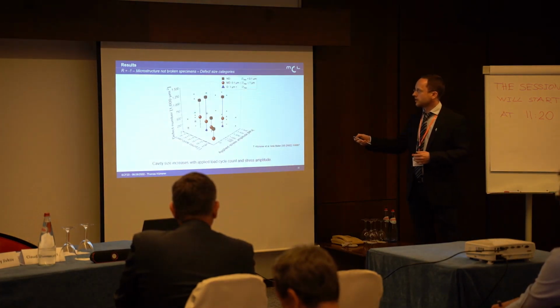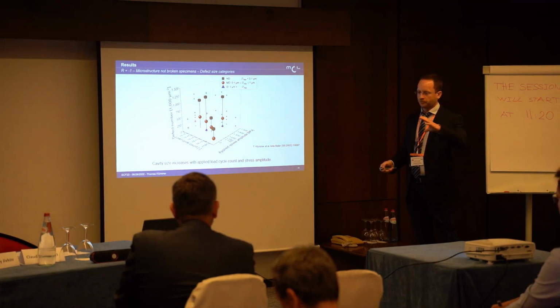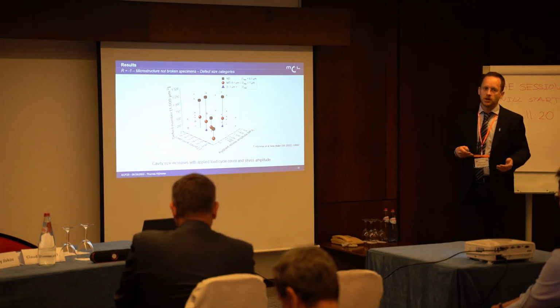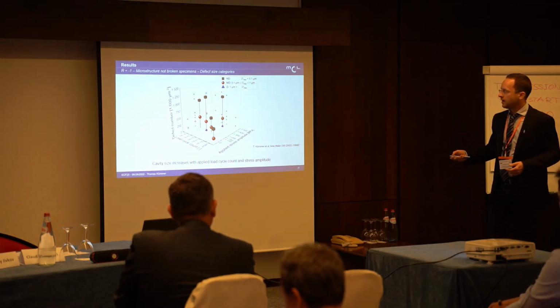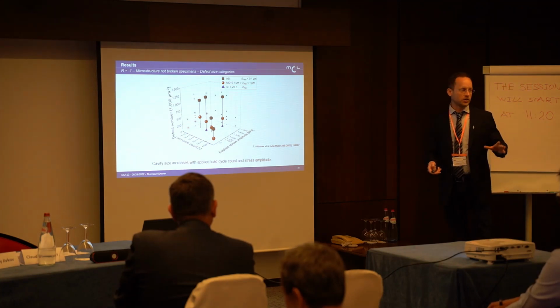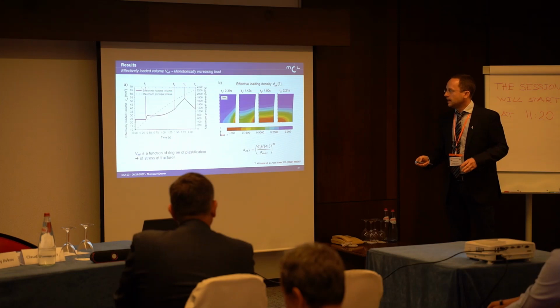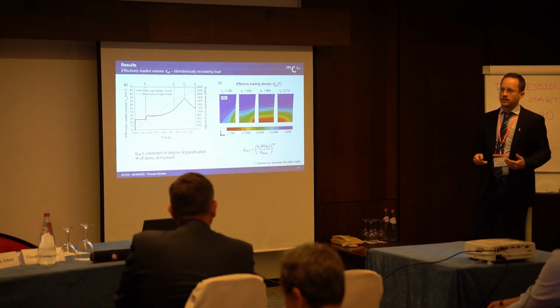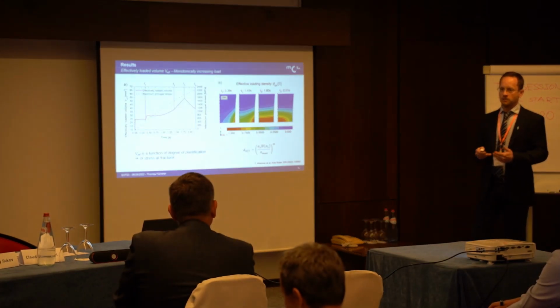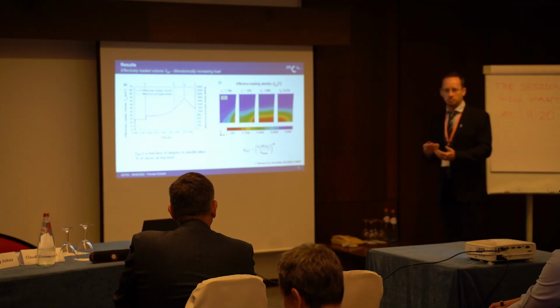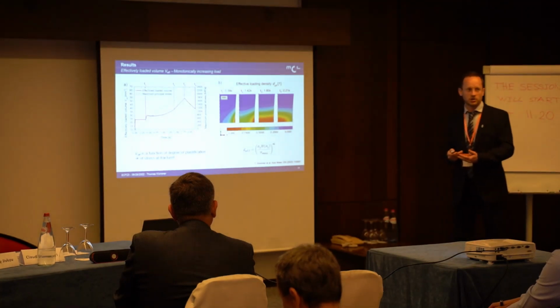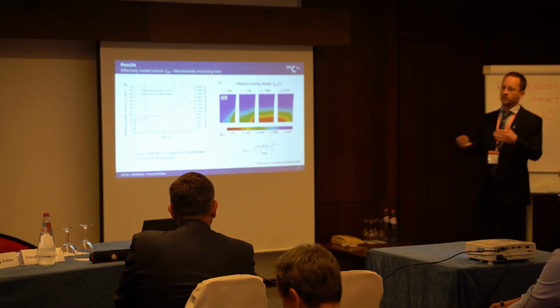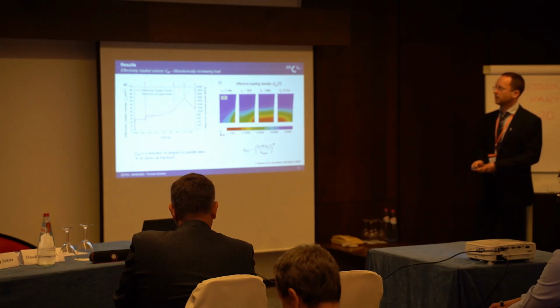But more interestingly, maybe here for the given sizes we looked at of the area, you see a rise with micro defects. So nano-defects merge to become micro defects. And for these defects, we didn't really have representative areas, much other areas we looked at. But still, it's interesting that these defects become large in number and may really play a role in these fracture processes, in these conditions relevant to the tooling I mentioned earlier.